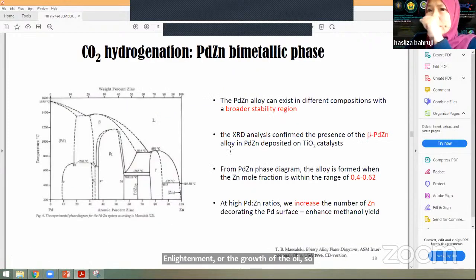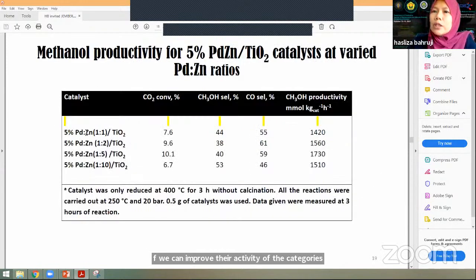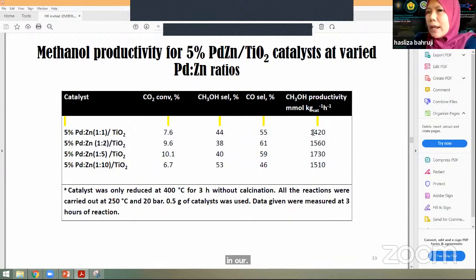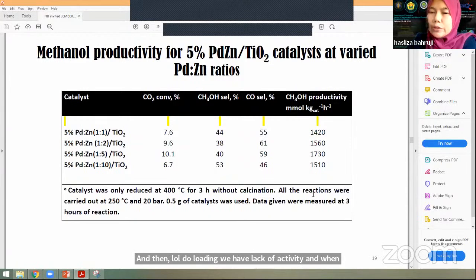So when we have a look at this phase, we can see that palladium zinc alloy exists in different compositions with a broader stability region. Basically, palladium zinc alloy can exist in different concentrations. It doesn't have to be a 1 palladium to 1 zinc ratio. It can have this range, which is from 0.4 to 0.62. So we try to vary the ratio of palladium to zinc to see if we can improve the activity of the catalyst. What we did here, palladium zinc on titania, was vary the ratio of palladium to zinc at 1 to 1, 1 to 2, 1 to 5, and 1 to 10. We have a look at the activity for methanol production, and it is clear that at the 1 to 5 ratio, we managed to improve the selectivity and the productivity up to 1,700 per hour. At low zinc loading, we have a lack of activity, and if we go much higher, we also reduce the activity.